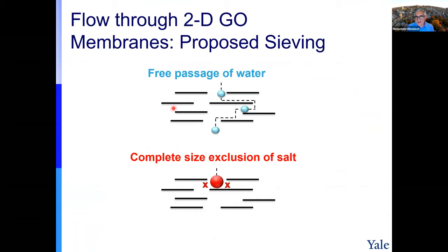You vacuum filter these nanosheets, and they will deposit nicely, ideally. And in principle, you will have only the water molecules going through all these tortuous paths. And the salt, because it's very big, if you create the spacing the right way, will not go through. And we were quite puzzled because we have seen all this literature, and people were not able to report very high rejection. It doesn't make sense how you can create such a thing ideally with no defects and have it as a membrane.